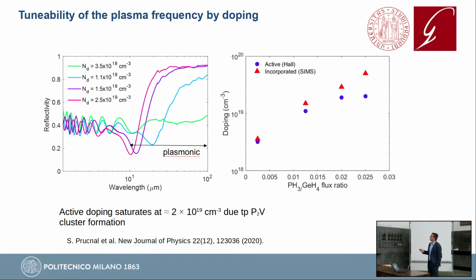So these are different samples with increasing doping level, going from a few 10^18 to a few 10^19. And then this doping was done in our deposition tool, adding phosphorus during growth. But then we noticed that adding more and more phosphorus was not giving any further shift. So we could not get away from this 10 micron plasma frequency.